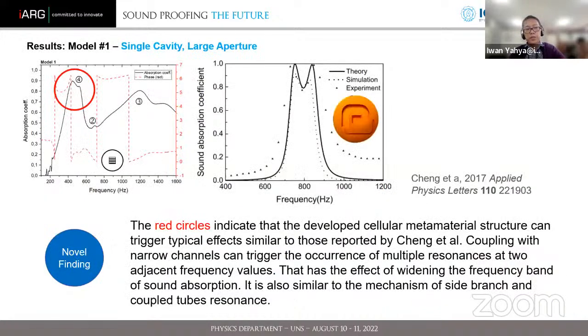If you see the red circles, they indicate that the cellular technology we have developed has a similar effect to the phenomenon reported by Cheng: if you are working with a narrow channel, sound absorption occurs at 2 adjacent frequencies. This is the typical response if we are working with coupled duct, coupled tube, and also side branch resonance.